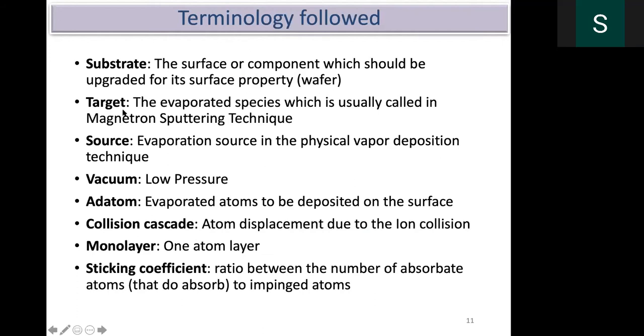Target: everybody thinks that target means you go and hit something. But in the case of the sputtering technique, the material which you want to evaporate is called the target material, which is loaded in the magnetron gun. When you power it, the magnetron gun will sputter the elements by way of momentum transfer. The ions bombard the surface and detach the surface atoms. Those atoms are ejected and go and deposit on the substrate.